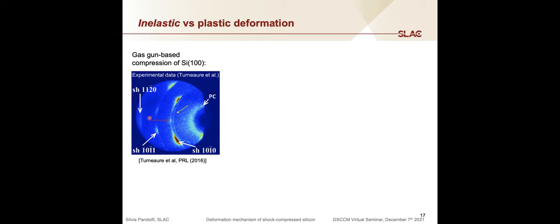Another thing that I wanted to stress is that the author also suggested that there could be more than one orientation relationship present in this data, which is in contrast with what we observed under laser-driven shock compression. However, we cannot directly compare the experimental data because this experiment has been performed in a slightly different geometry and uses a pink beam.